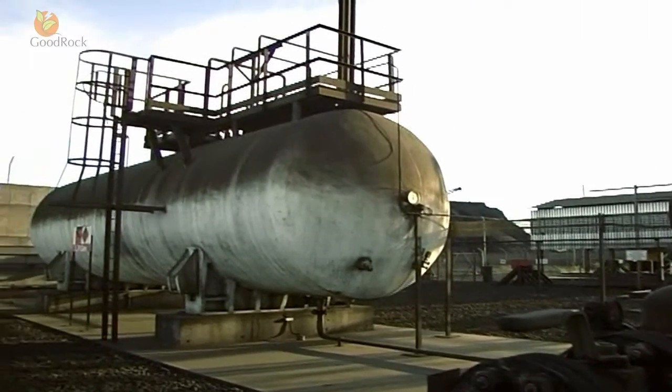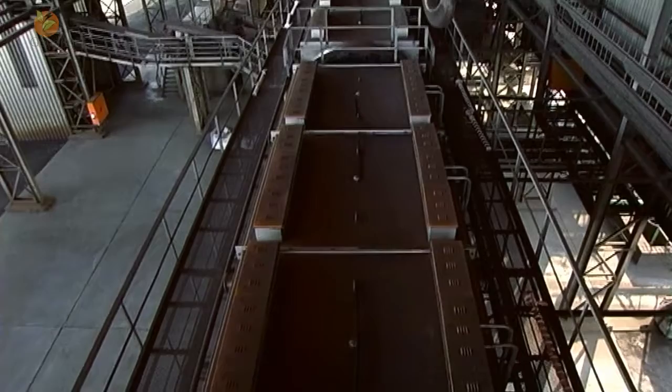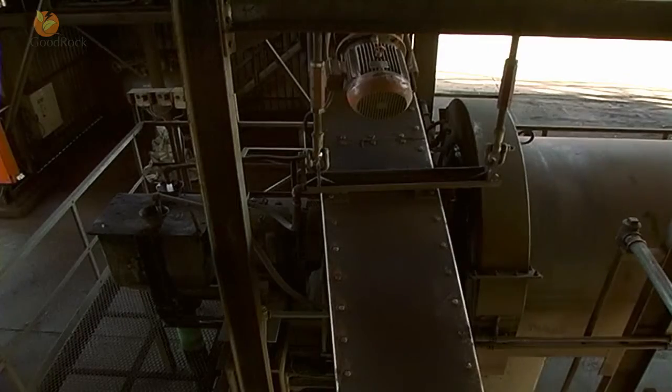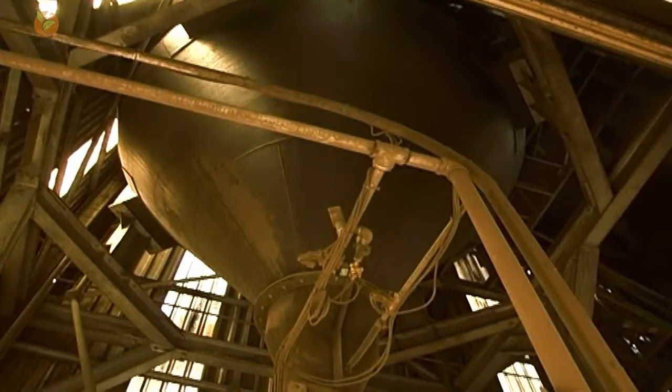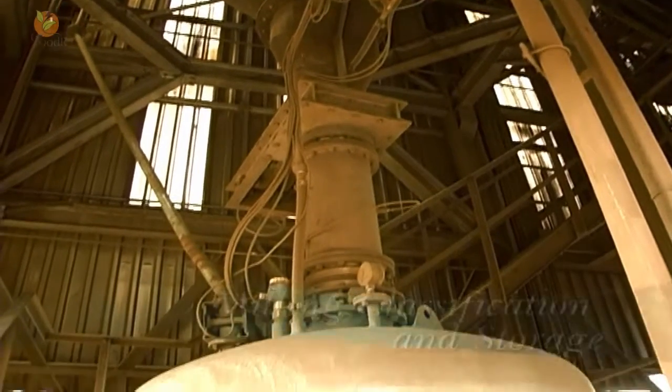The calcining reduces the manganese ore to produce manganese oxide. This reaction proceeds when external electrical heat of approximately one megawatt, combined with another megawatt of internal heat generated by a liquid petroleum gas burner, is applied to the 25-meter long rotary kiln.